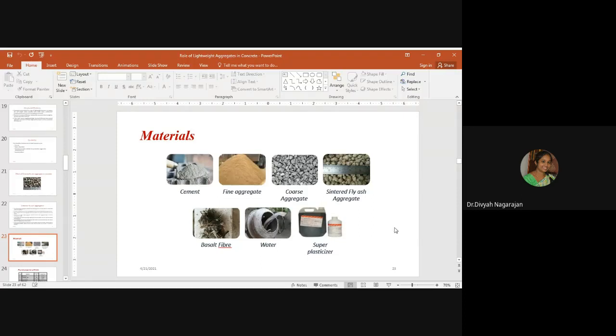The basalt fiber, as I said earlier, is added to this lightweight concrete in order to make it fit for use in structural applications. Although the sintered fly ash aggregates are good in split tension and flexural characteristics, there is some reduction in flexural strength when it is used in structural members. So this particular fiber is used to improve the split tension strength and flexural properties of the concrete. Most importantly, we have seen in the crack pattern that the crack passes through the matrix interstices of the aggregates, and it will cause problems with bond. So when fiber is added to this concrete, this problem can be reduced. Then water and superplasticizer are used in this investigation.